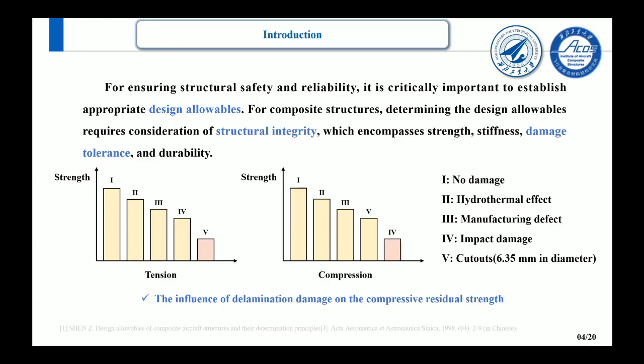Improving damage tolerance primarily involves assessing the residual strength of the damaged structure. Research indicates that composite structures can experience a significant reduction in residual compressive strength after impact loading. Composites have relatively weak interlaminar properties, making them susceptible to delamination damage on impact, which severely compromises their compressive performance. Furthermore, studies have shown that delamination defects account for a substantial portion of defects during the manufacturing process of composite structures. Therefore, it's critical to investigate the influence of delamination damage on the residual compressive strength.